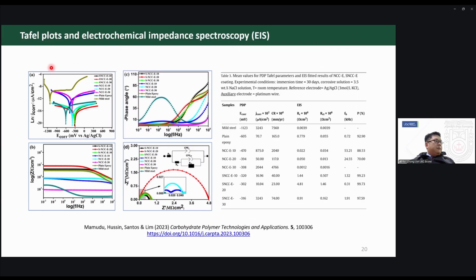So from the PDP, you get Tafel plots, this figure here. You have the anodic part, the cathodic part, and where it dips is an estimate for the corrosion rate. So the position of this type of process can give you an idea of the performance. Normally, if you want good corrosion protection, you want to go to the right in the way this is plotted.